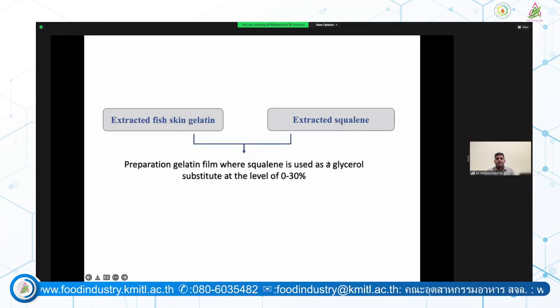So generally, when we prepare the gelatin film, we need to add glycerol at 30% of protein to plasticize it, to make the film more flexible rather than rigid. In packaging, flexible films are highly preferred. So we add glycerol up to 30% of the protein weight. But this 30% of glycerol will significantly increase the moisture property, which is undesirable in the packaging industry. To replace this, we have substituted the glycerol with squalene. We tried to study the